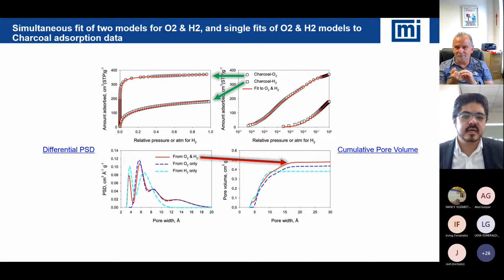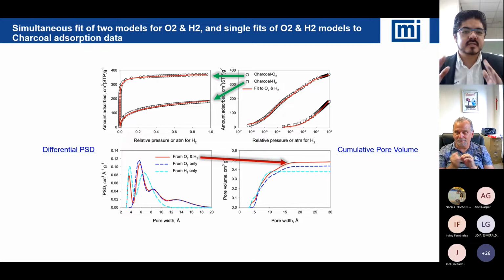Yeah, because sometimes we see a pore size distribution that is too sharp, or that has almost no pores at 10 Angstroms or 20 Angstroms, which is, I think, something related to the calculation.